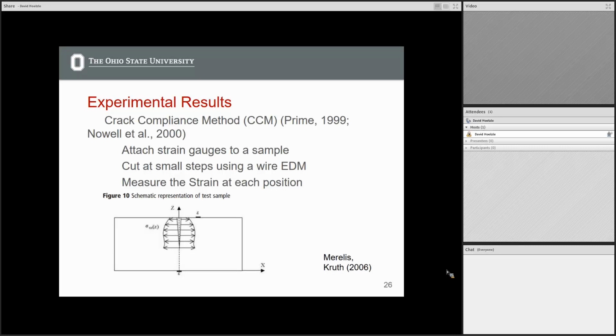But the main overall idea of this method was that by attaching a strain gauge to a sample, you're able to cut the sample that has a pre-stress in it using a wire EDM process at very specific depths. And then by measuring the strain, you're able to backtrack and get the residual stresses that are built up throughout that part.